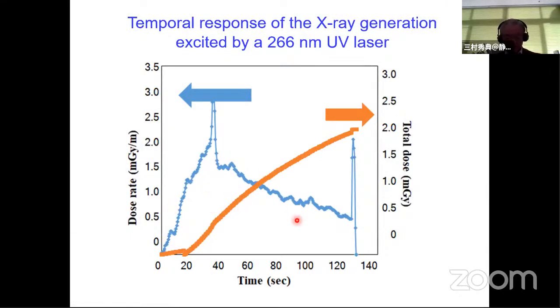This slide shows the temporal response of the X-ray generation excited by 266 nanometer UV light. This line indicates the dose rate, and this line indicates the total dose. When the laser is irradiated, X-rays are generated and the dose rate gradually increases. The maximum dose rate of about 3 milligray per minute was obtained, and a total dose of 2 milligray was obtained over 130 seconds. The X-ray generation increased at first and then gradually decreased, even though the lithium niobate crystal was still excited by the pulsed UV laser.